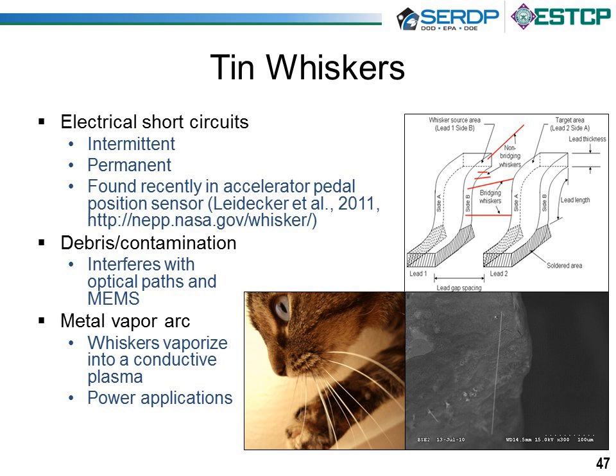They also result in debris and contamination. If you've got optical paths or MEMS circuitry, you want to pay attention to where you're dealing with whiskers. On the other side of the spectrum, it can result in metal vapor arcing. So if you've got a lot of power, instead of just melting a whisker, you vaporize it. And when you vaporize it, it forms a conductive plasma that can conduct many hundreds of amps. It's quite a destructive failure mode, so we want to be watching out for that.